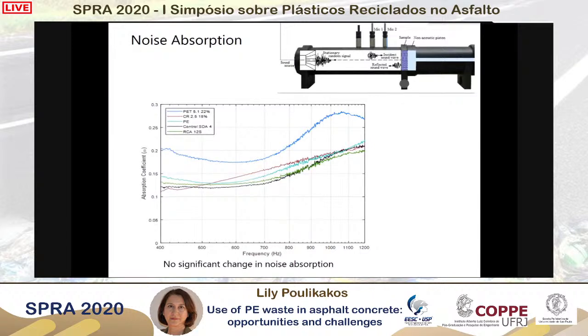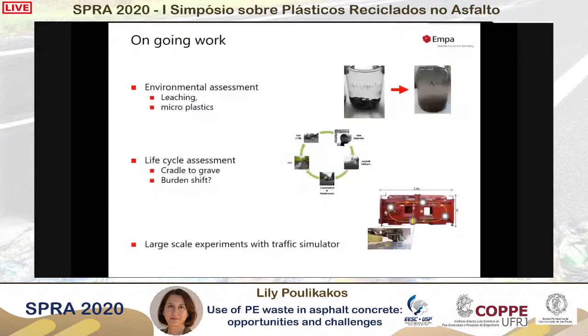Then another parameter that we're looking at is noise absorption properties at various frequencies, that is done with a tube test that is shown on the top. Again, this is a result for various mixtures that are used in our project, and the PE modified mixture here shown in cyan does not divert too much from the black one at the relevant frequency range. So also we can say that there is no significant change in the noise absorption property. So we did not lose any noise absorption property by using PE as a waste material in our mixture.